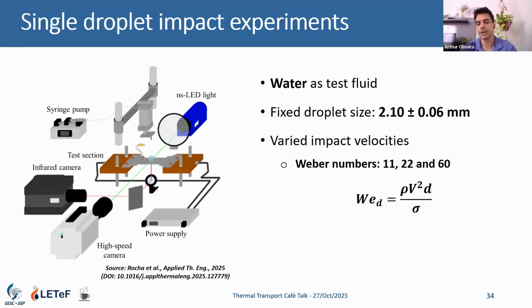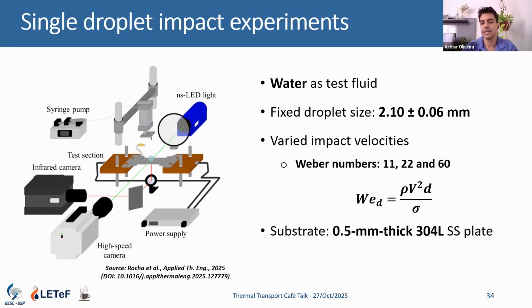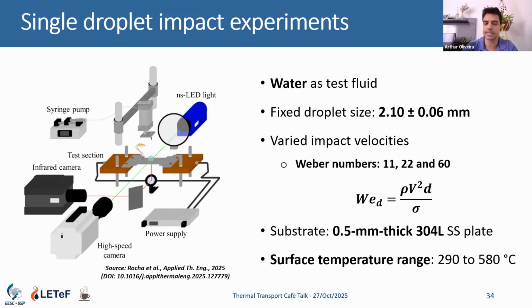We have water as the test fluid. We have a fixed droplet size of 2 millimeters. We vary the impact velocity by changing the droplet release height. And the plate was a 0.5 millimeter stainless steel plate.